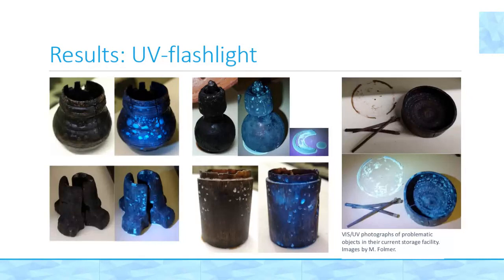These objects looked nearly black, and using my flashlight, I again saw droplets covering the surface. Here are some examples of objects with a large amount of residue visible on the shelf as well. These objects were stored in this location in 2016, in case of this object here with its lid. This object was lent out to a different museum and returned in 2018. Therefore, the leaching that we see and this residue that has formed on the shelf is very recent and has occurred here in the past 3 to 5 years, indicating that this leaching is an ongoing process.